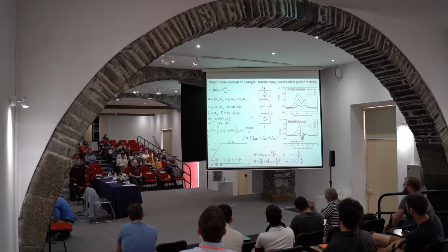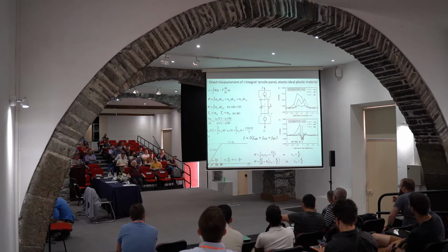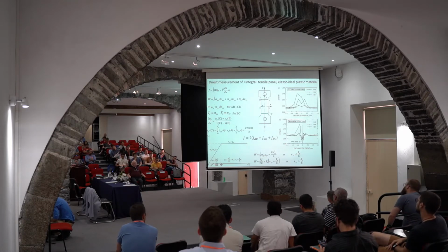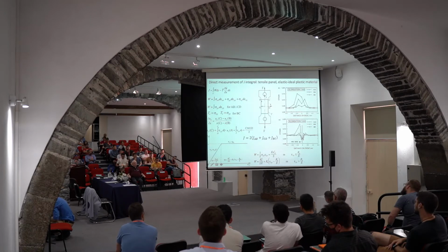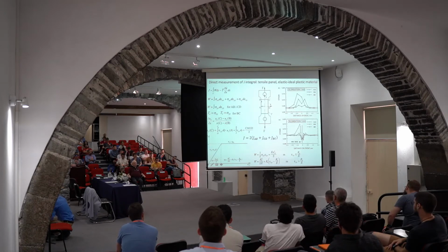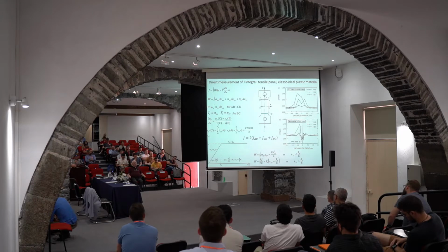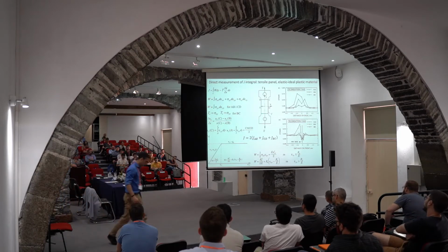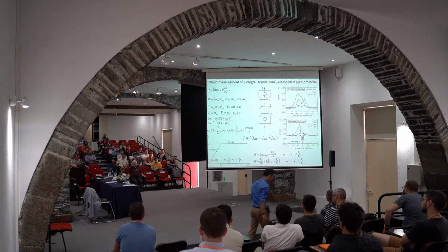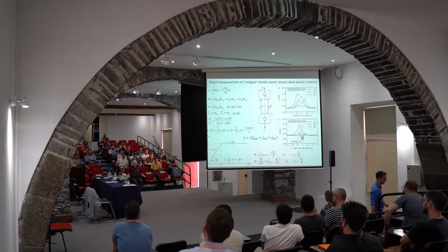Of course, also in combination with crack mouth opening displacement, which we definitely also need to measure, and which is relatively simple in addition to strain gauges. So we can reduce J integral to measurement of strain gauges and CMOD. At that time, when this was a bit popular, it was done by strain gauges, of course. Nowadays, this can be done with digital image correlation, but surprisingly, nobody is doing it.